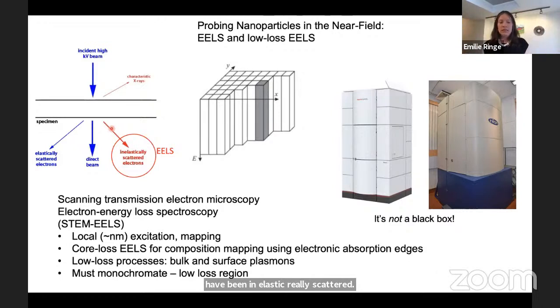This process can be anything from, say, a core loss process, such as an electronic absorption edge at quite high energy, to a bulk or surface plasmon. So you're mapping the energy loss at the nanometer scale, and that tells you something about the behavior of this material in the optical range or in the electronic absorption edge range.